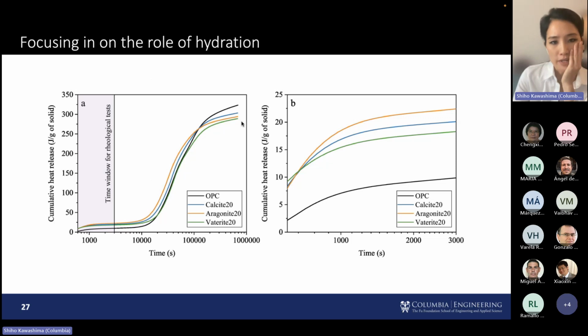So remember before we were kind of just focusing in on this area, or that's where I was pointing your eyes. But calcite has the highest cumulative heat release of all the systems with the calcium carbonate, right? But then remember there was a crossover point. So if we zoom in to the cumulative heat release and the time window for the rheological tests, then aragonite has the highest heat release.